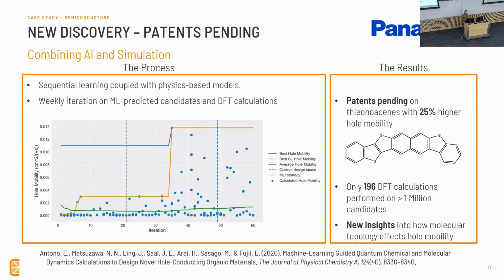The orange line corresponds to the best thing that the machine learning model and this DFT has found within the program itself. So we were able to start pretty low, as you can see, pretty close to 0, but then we were getting better and better until we hit like this wall at about iteration 6 or so. And I'll get into some detail about why that was. But then each of the points corresponds to a given iteration. These were the calculations that Panasonic ended up doing as part of their DFT.